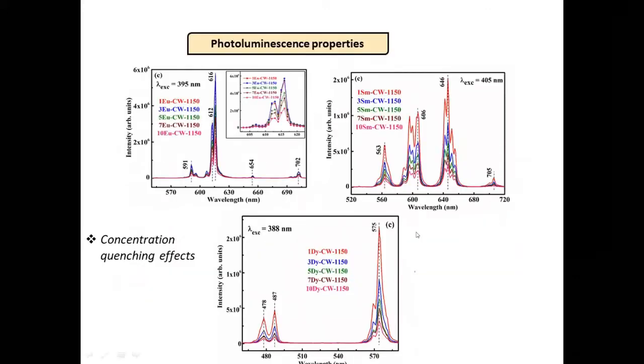And here again we see that as you increase the dysprosium concentration in your calcium tungstate matrix, the photoluminescence intensity falls. This is a result which is different from that observed in glasses. In glasses, we don't see concentration quenching effects with dysprosium ions and europium ions. But in crystalline materials, we are seeing those concentration quenching effects. The photoluminescence intensity falls with the increase in the rare earth oxide concentration.